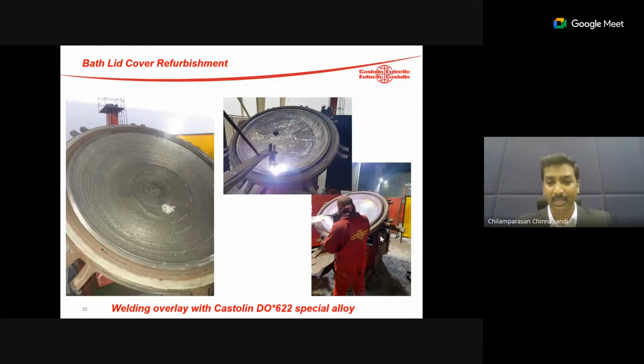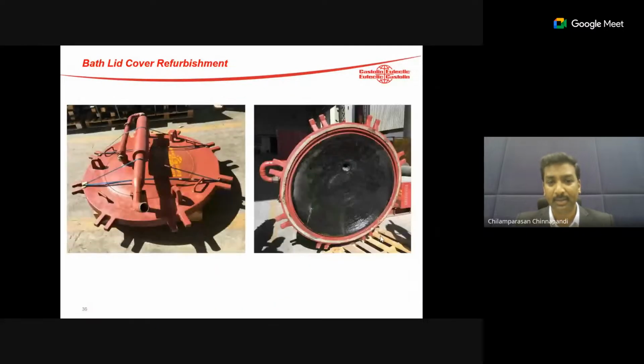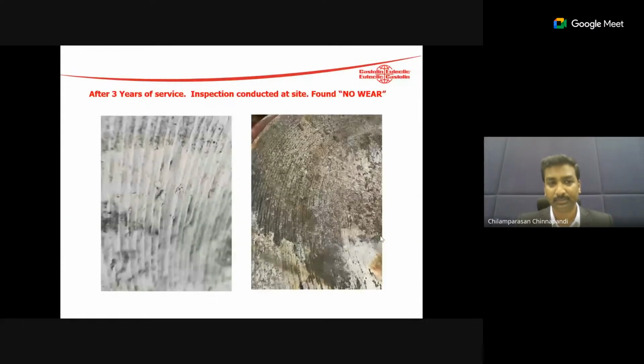It withstood what we gave in one of the trials, and the customer has got up to 4 years of life. It started from 15 days, and they have got 4 years of life, which means they can avoid the complete repairing process, the component will be available anytime, and it's a one-time investment. So this is after 3 years, and now it's going to cross 4 years. It is still in intact condition. You can see the weld bead here as well.